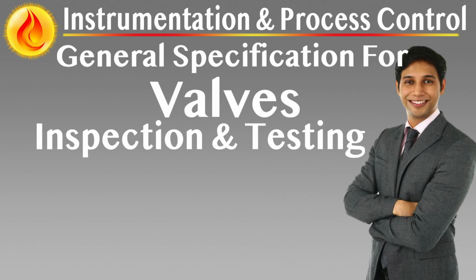Where destructive tests such as sectioning or metallography are required, for example, to qualify overlay procedures or verify weld penetration in critical sealing surfaces, they must be performed on sacrificial samples representative of production valves. The supplier shall provide full reports, including etched cross-sections, weld maps, and metallurgical analysis to validate conformity with design requirements. These tests form a key part of type qualification and are typically not repeated on production units unless otherwise specified.